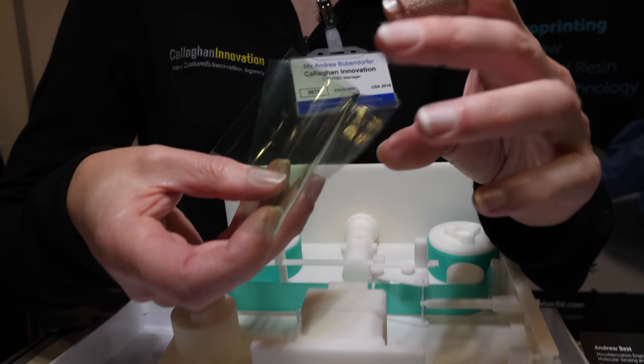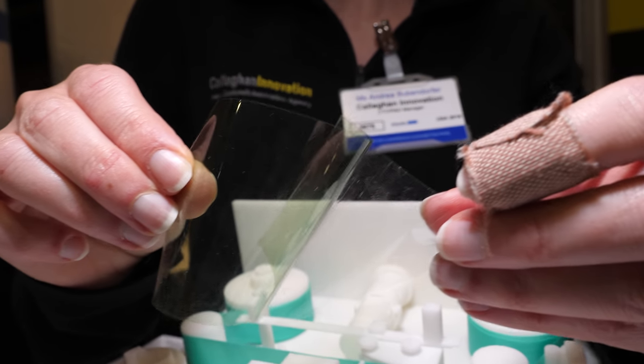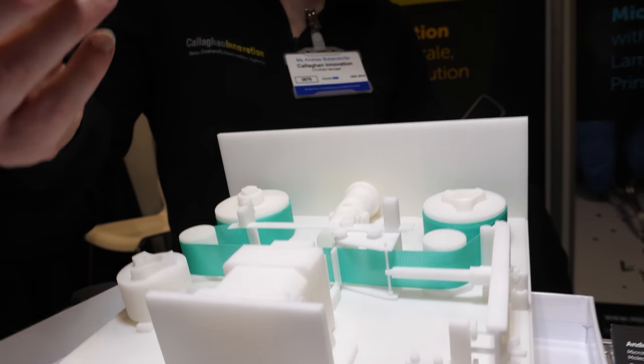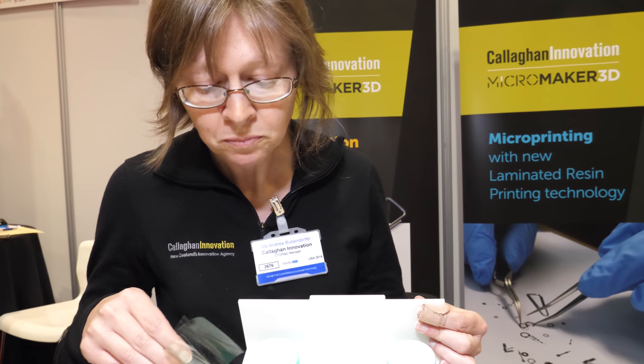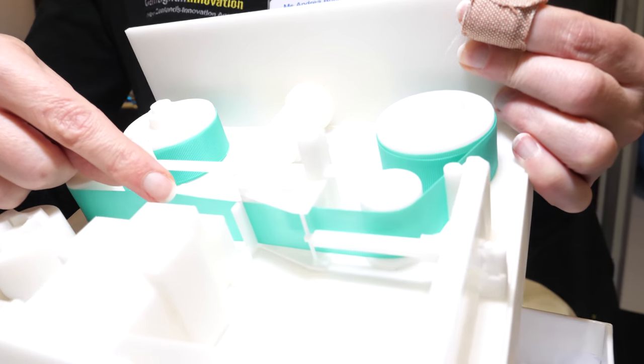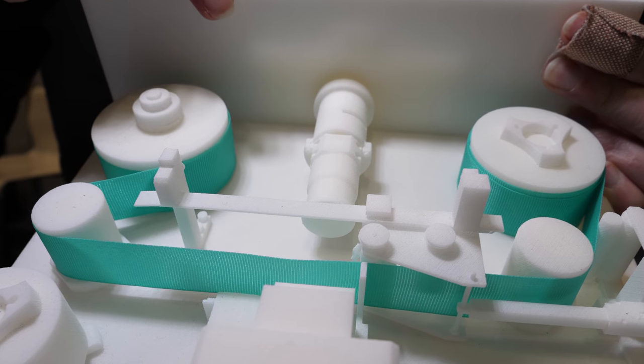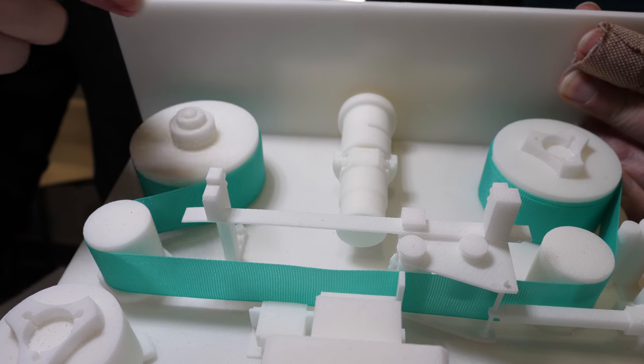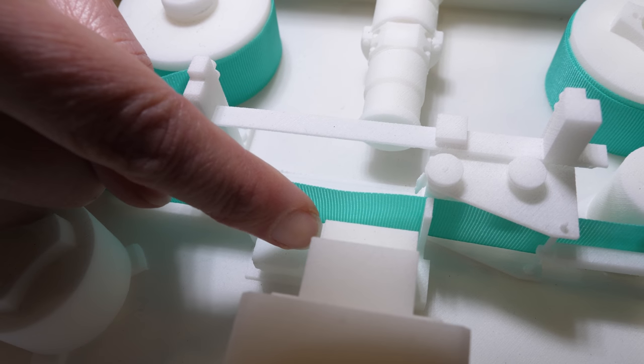We take a photoresist-quality dry film — a 5 micron high-quality film able to withstand continuous operating temperatures from minus 60 to plus 200 degrees Celsius, resistant to all known acid solvents and bases. This is supplied on high-volume rolls. We put this on a roll through the machine, rolled across with one support material removed and transported — the ribbon symbolizing the film material we use. Each layer of the 3D print is exposed with a special UV projector that activates a particular area in that film. Once that area's been activated, which takes about three seconds, laminated rollers move across and laminate that stack down onto the print bed.